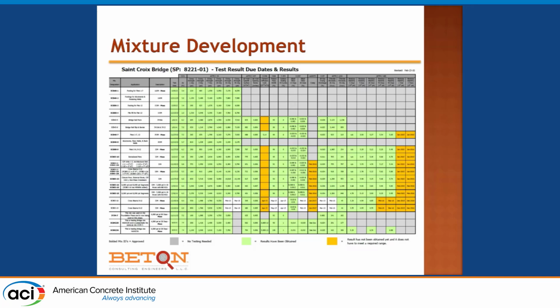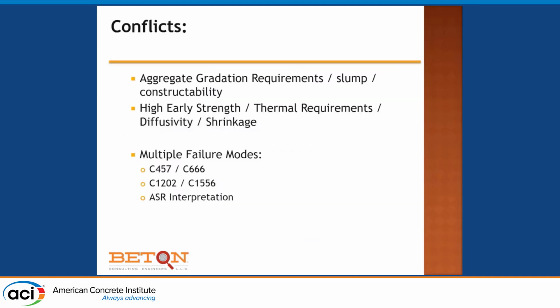And we had developed just a few concrete mixtures. The comment for those reviewing is that we could not read the slide. But the purpose of this, of course, is looking at the number of test requirements, not what they individually are. We have some conflicts. We have a conflict between the gradation requirements that we set, which deviate well outside of what MnDOT is used to seeing. The slump, which we don't care about because we have the 0.33 water cement ratio and 240 pounds of water. We are using our best friend, polycarboxylate, and constructability, because if you look at these concretes, they look very harsh, very rocky. If you look at them on paper, right? If you look at the mix design, it looks really rocky. It pumps like a dream because we developed our mixtures from a packing model.